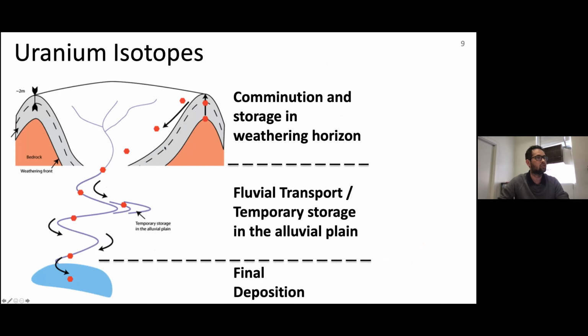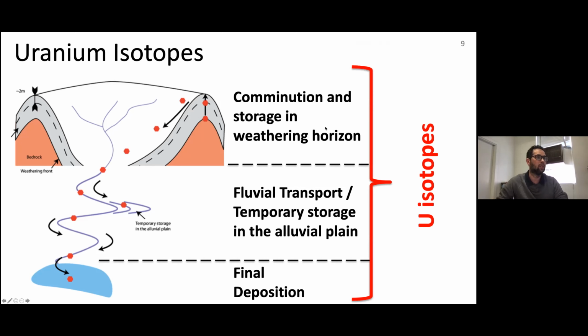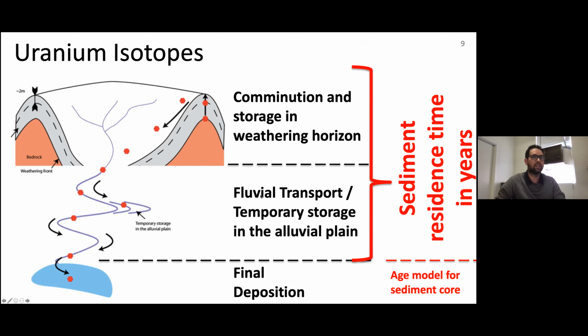So if we think about what happens in a catchment, we have our bedrock, we have a weathering horizon profile, where we actually produce a comminuted bedrock and produce fine powder just at the interface between the bedrock and the weathering horizon. We will then have some storage in the weathering horizon, hill slope transportation, probably some fluvial transportation, and then final deposition. So with the help of these uranium isotopes, we can essentially quantify the entire time between comminution and present days. So since we're working in lake sediments, we can also infer the chronology of our lake sediments. So we get an idea about the age model of our sediment core. And if we account for this time since deposition, which has nothing to do with catchment erosion processes, obviously, if we exclude that, we can estimate what we then started calling the so-called sediment residence time in years. And this, since it accounts for the time between formation of fine powder and final deposition in the lake basin, is a measure for catchment erosion.